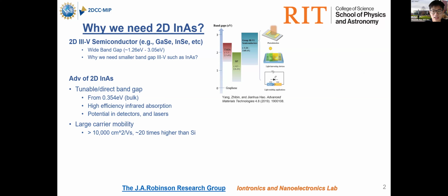However, indium arsenide as a III-V material is actually sitting in the opposite corner of III-V materials, where it has a super narrow bandgap. So why do we care about using indium arsenide? The advantage is that it has a tunable and direct bandgap. Even though it has a really small bandgap, it is highly sensitive to the infrared range because of such a narrow bandgap, which gives great potential in detectors and lasers.